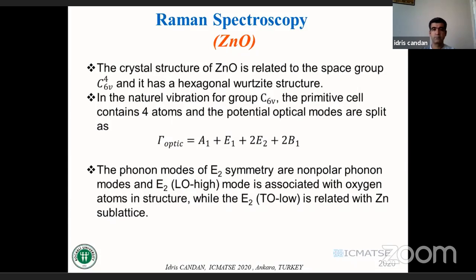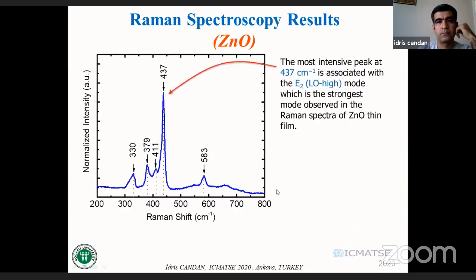And it has a hexagonal wurtzite structure. The primitive cell contains 4 atoms and the potential optical modes are split as Γ optic equal to 1 A1 and E1 plus 2 E2 and plus 2 B1. The phonon modes of E2 symmetry are non-polar phonon modes, and the E2 high mode is associated with the oxygen atoms in the structure, while the E2 low mode is related to the zinc sublattice. In our measurement, the most intense peak at 437 per centimeter is associated with the E2 high mode, which is the strongest mode observed in the Raman spectra of the zinc oxide thin film.